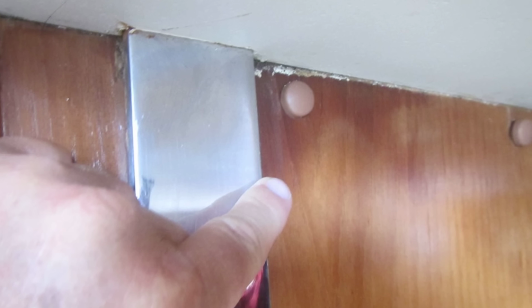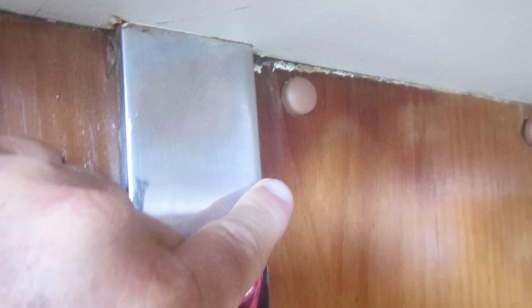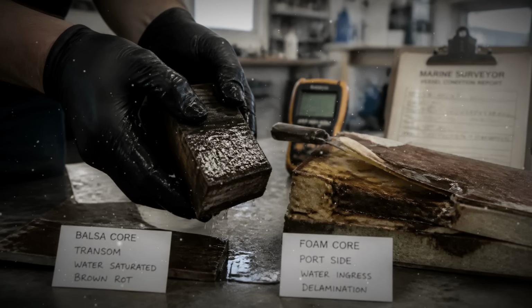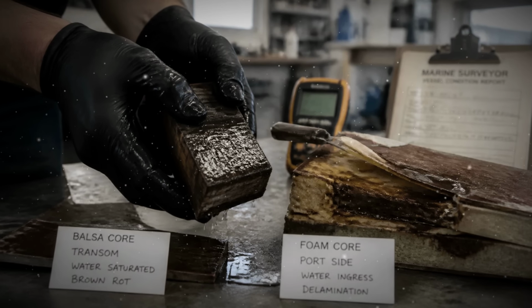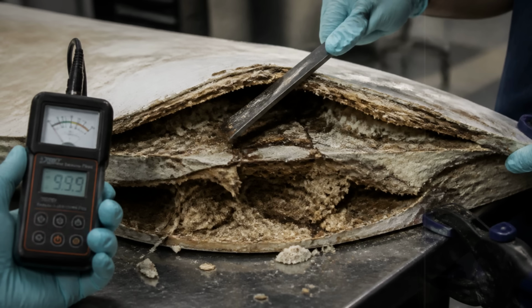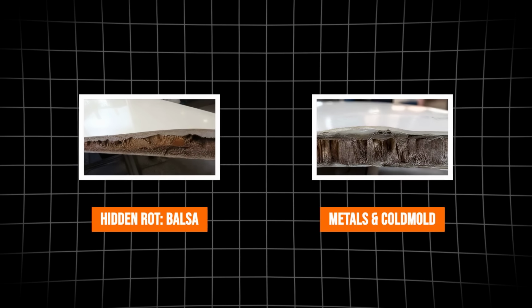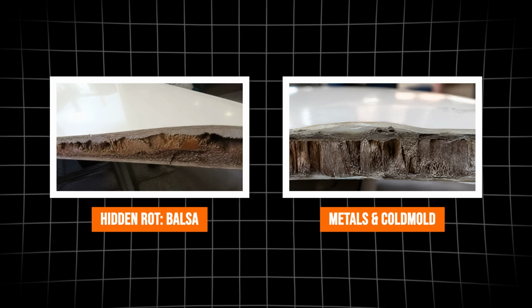When water intrudes through a deck fitting, a chain plate, or a through hull into a cored hull, the core absorbs it. Balsa rots. Foam delaminates. The structural sandwich separates from the inside. The hull feels solid on the surface while the core turns to mush behind it.